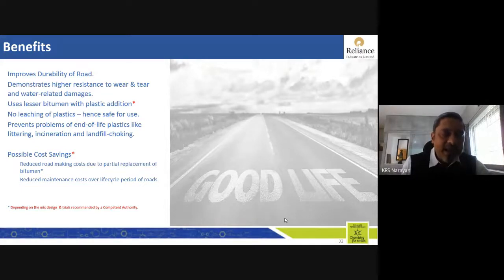So I think there is a caveat in it. It has to be approved by the competent authority. The mix designs have to be carried out. The Marshall Stability Index has to be carried out. The tensile strength and the compressive strength have to be tested to ensure that there is a replacement of bitumen with plastic. So that is left to the competent authority to approve. And since it was our own in-house project, we took a decision that we will use 10% reduced bitumen.